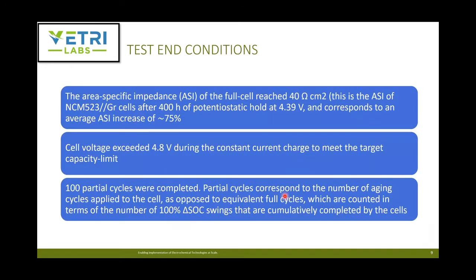The test end condition. So what did they call as the test end? There were 3 conditions they used. When one of these conditions is met, they call the test to be complete. The area specific impedance of the full cell reached 40 ohm centimeter square, which corresponded to a 400 hour potential static hold at 4.39 volts. This turns out to be about a 75% increase from the initial area specific impedance. When that's reached, they called it done.